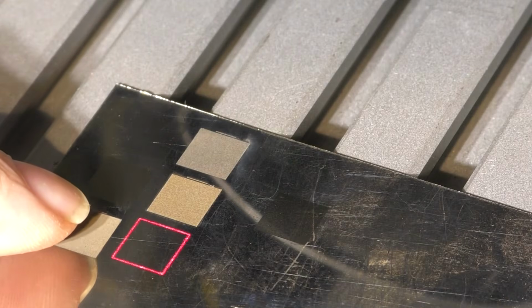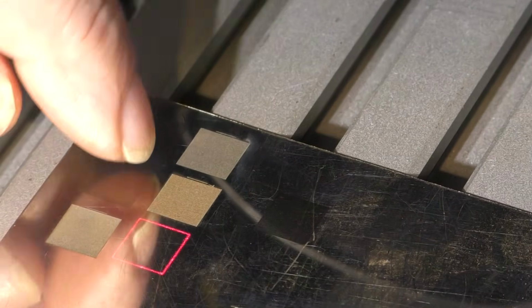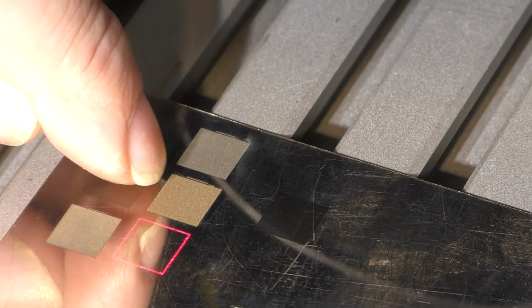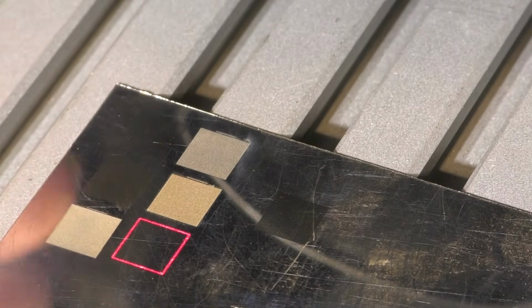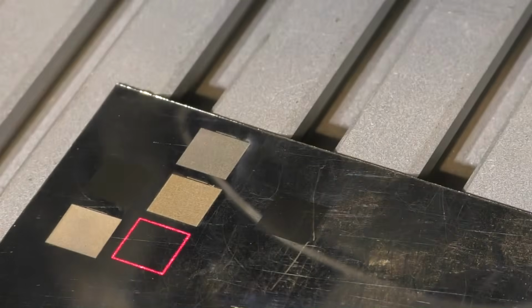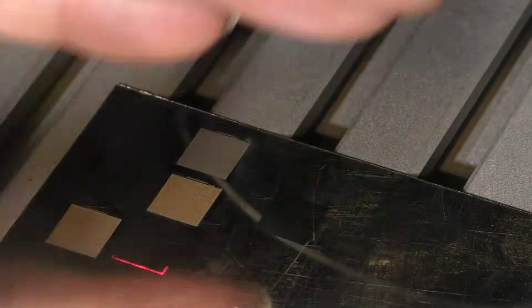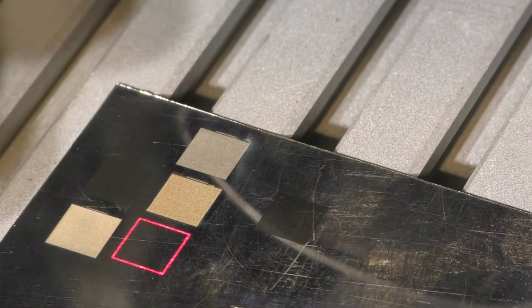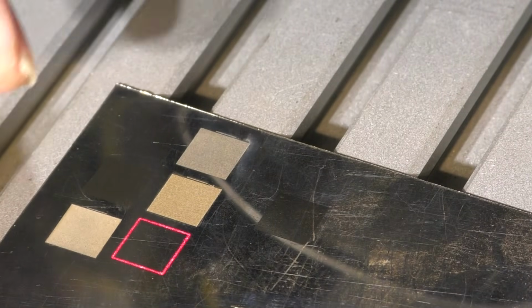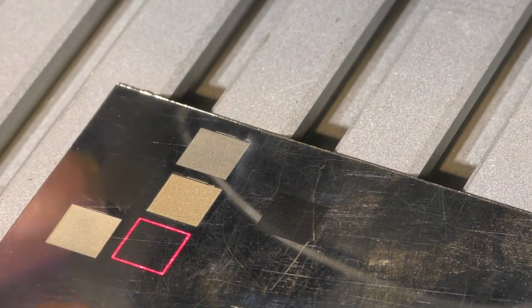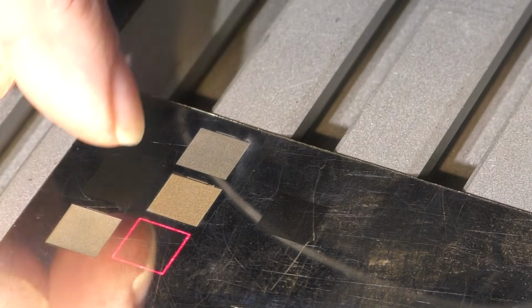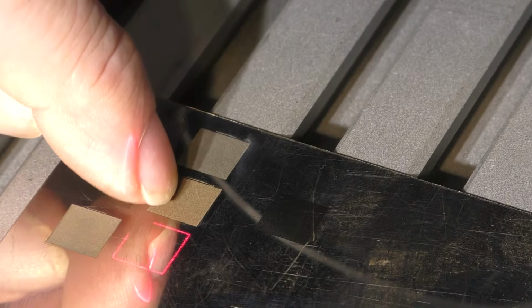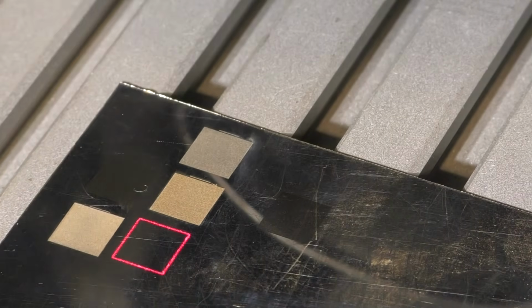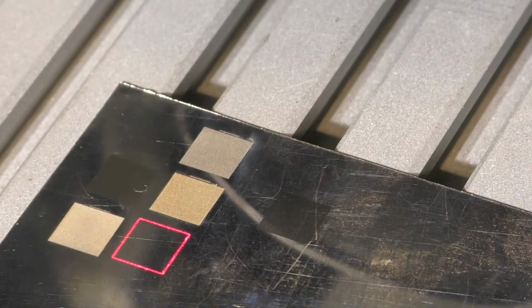Let's forget that mistake that I made there. In this horizontal direction with that one, we increased the power to the surface by approximately a factor of 4. So what I'm now going to do is modify this one by changing the line spacing from 100 microns to 25 microns, which again has a ratio of about 4:1. So we should find that we come out with more or less the same colour as this one, because we've got the same amount of power going down per square millimetre.